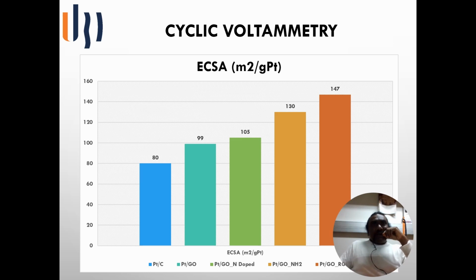and we have analyzed these materials through electrochemistry, cyclic voltammetry curves. We have extracted the electrochemical active surface area, which is 147 for platinum nanoparticles on RGD functionalized graphene oxide. This is the highest we have got among all the functionalized graphene oxides.